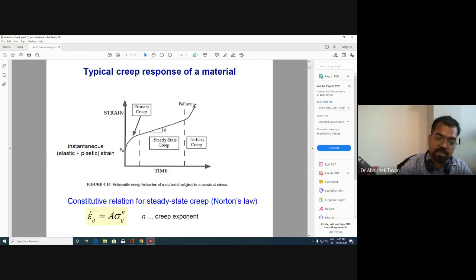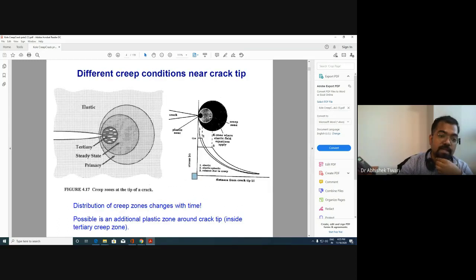As these stresses are increasing, you can imagine what will happen. If you increase the stress, you will suppress the primary creep. You might also suppress the steady state creep, and you can directly jump into tertiary creep. A similar thing will happen here. In this area, you are further away from the crack tip, so you will not have very high stress, although sufficient stress to start the creep. So in this part, deformation can be in primary creep.